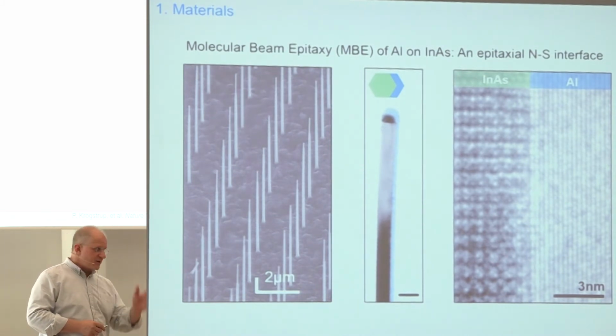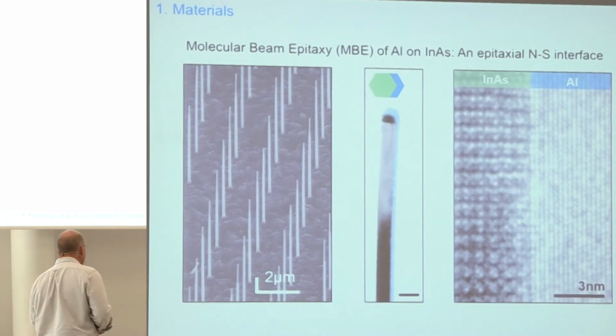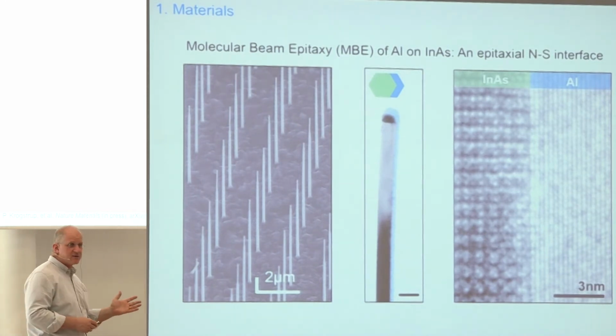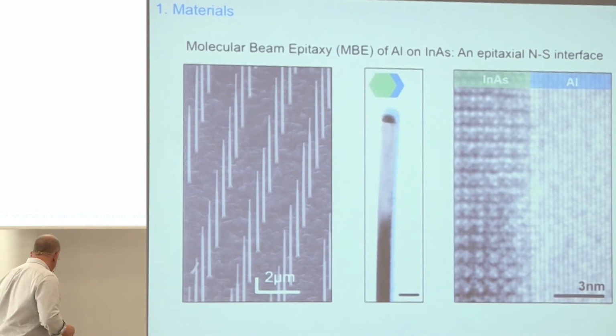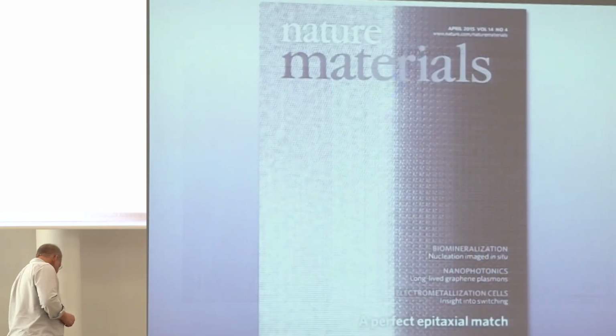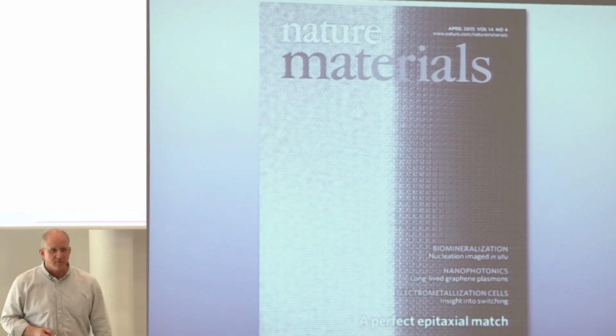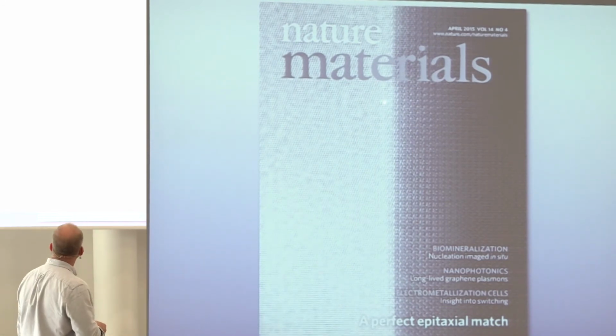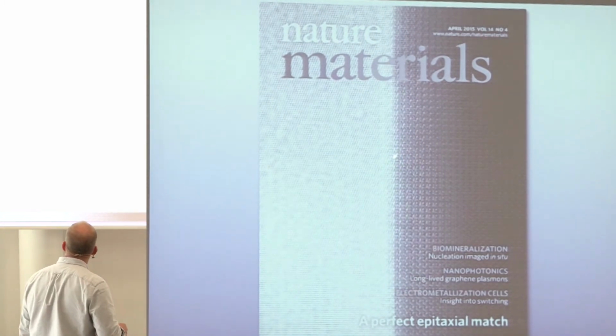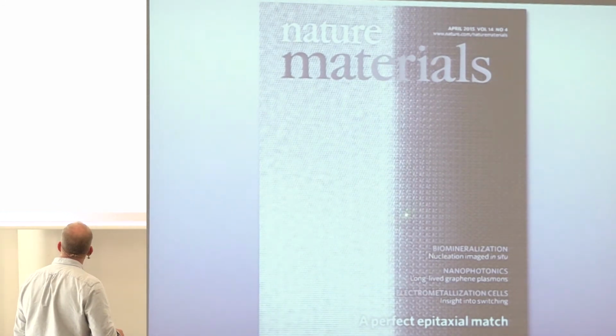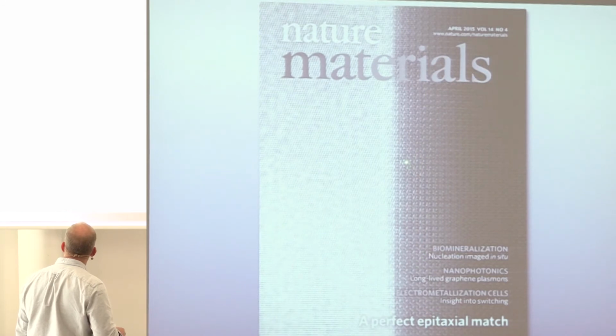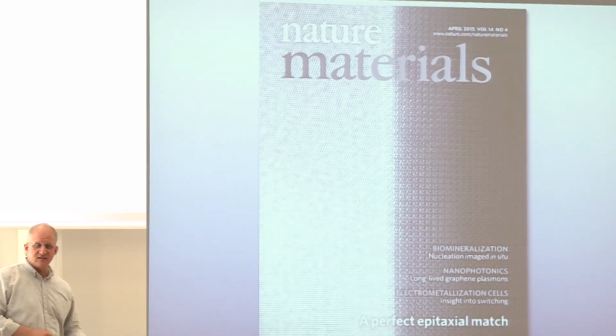That is, it will grow with atomic registry between the aluminum, which is not lattice matched to the indium arsenide, but it will find an angle to lattice match to it. And I should say, this is, I would say, a remarkable discovery. This is the current issue of Nature Materials, and there's a picture of that interface. And you can see from this picture what a remarkable interface it is. Here's the indium arsenide with its complex crystal structure. This is a transmission electron micrograph, and aluminum on the other side. And it just finds the angle that produces the epitaxial match to save energy, and it has to be done at just the right temperature.